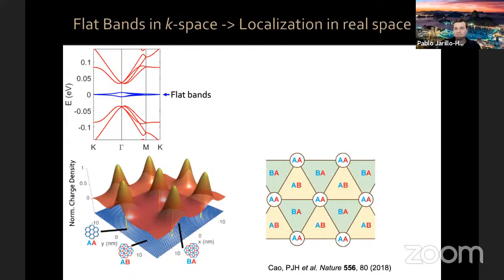Mm-hmm. Very good question. Well, first of all, many groups have mentioned that the twist angle disorder is very large. Very small or very large compared to what? You know, the first characterization locally over a large device of the twist angle was done by my group in collaboration with the group of Eli Zeldov at the Weizmann Institute. And we see that in a device that is very disordered in quotes, okay, but still exhibits superconductivity, the angular variation is of order 0.1 degree. Now, you may think 0.1 is very large, or you may think it's pretty small. Try to draw two lines parallel to each other within 0.1 degrees, you will realize it's not that large, okay? So that's one thing. Now, it is true, however, that given that this magic angle physics occurs mostly between 1 and 1.2 degrees, if you have a lot of disorder, then you're not going to see this physics, okay? If you have, on average, 0.2, 0.3 degrees variation, it's going to be hard to see this physics, okay?